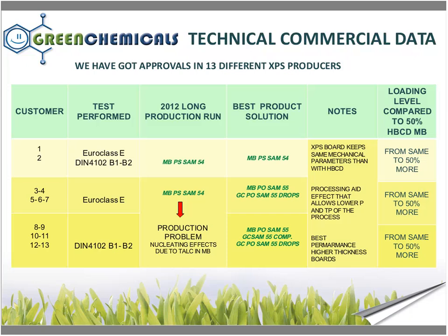We can notice a processing aid effect, which allows a lower process temperature and may help when CO2 technology is used for producing XPS. We have also noticed better performance of our solution as the thickness of the board increases, probably because of the processing aid quality and better compatibility with polystyrene than HBCD. Concerning loading level, we talk about a product which is not as active as HBCD, so we go from the same amount when the XPS producer is able to use a highly concentrated version towards 50%, and this is heavily dependent on the thickness of the board.